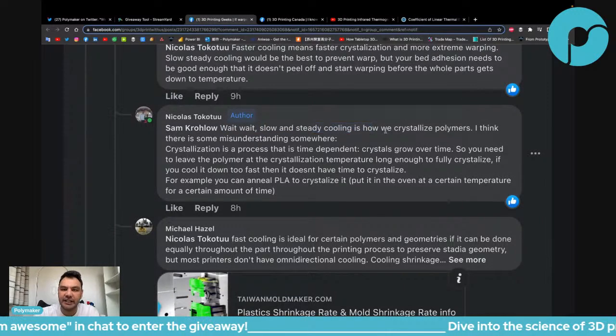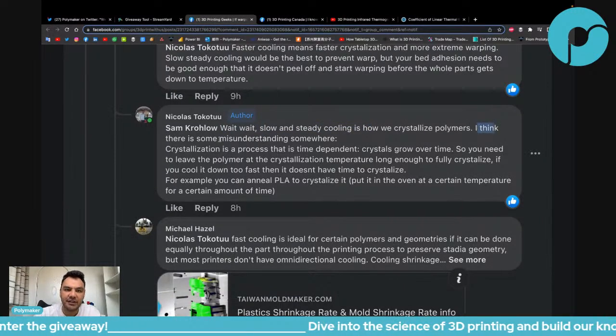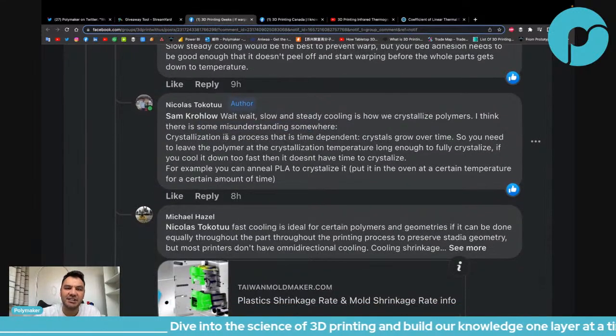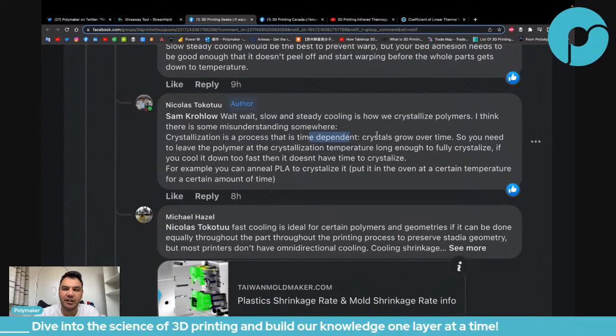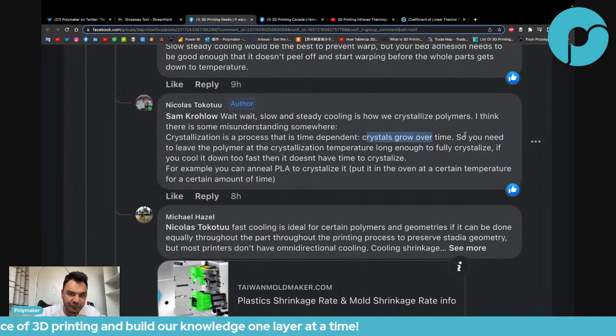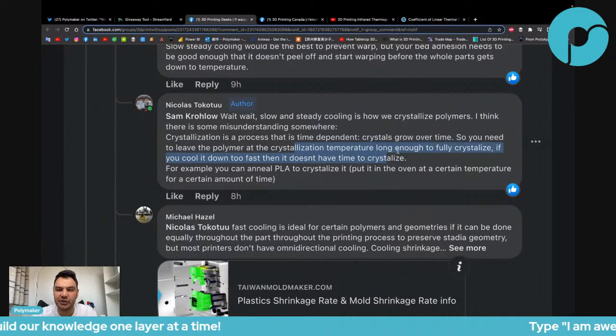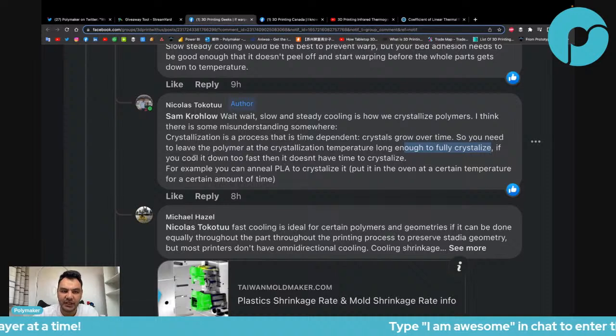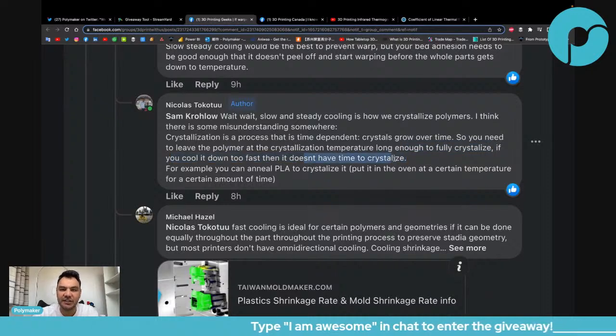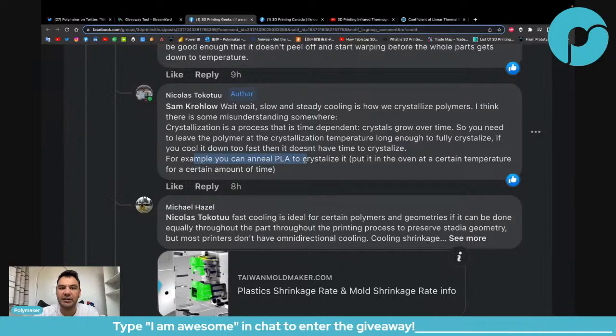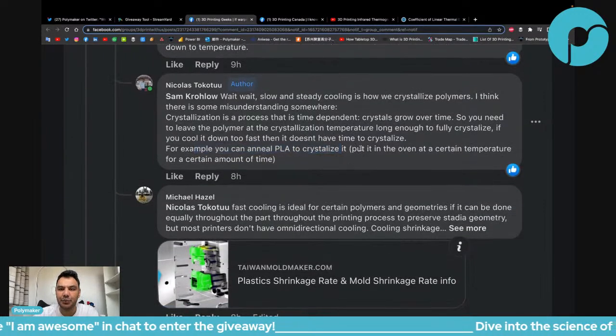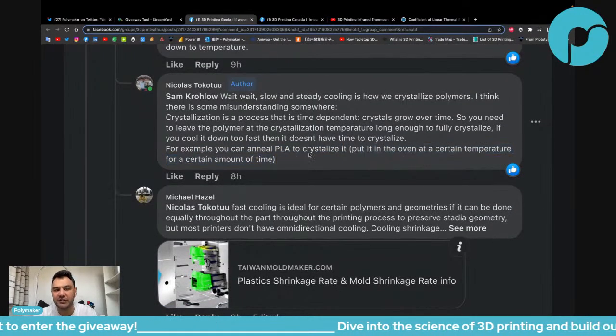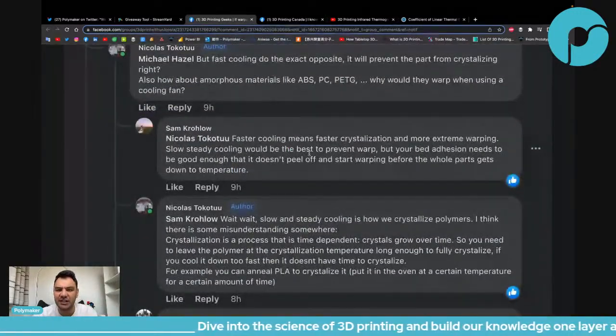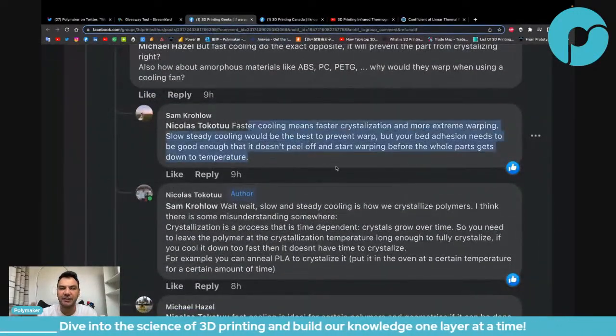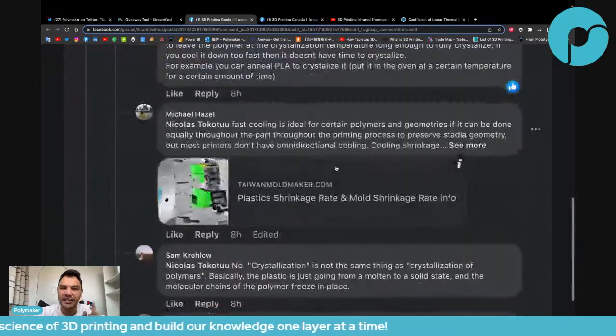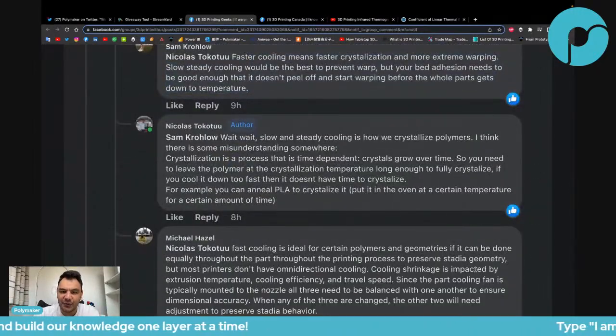Let's finish that explanation. Wait, because I was completely lost. Slow and steady cooling is how we crystallize polymer. I think there is some misunderstanding somewhere. Crystallization is a process that is time dependent. Crystals grow over time, so you need to leave the polymer at the crystallization temperature long enough to fully crystallize. If you cool it down too fast, then it doesn't have time to crystallize. For example, you can anneal PLA to crystallize it: put it in the oven at a certain temperature for a certain amount of time. So I wanted to clarify what crystallize means, because we were thinking completely opposite stuff. And then I realized why we were thinking differently.